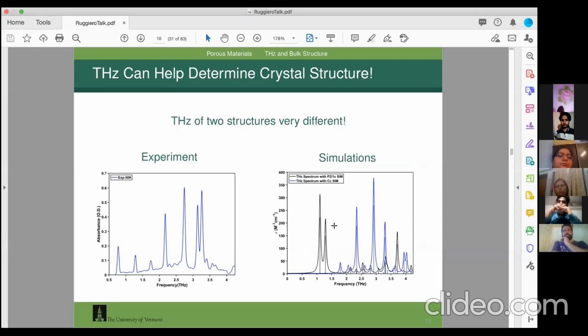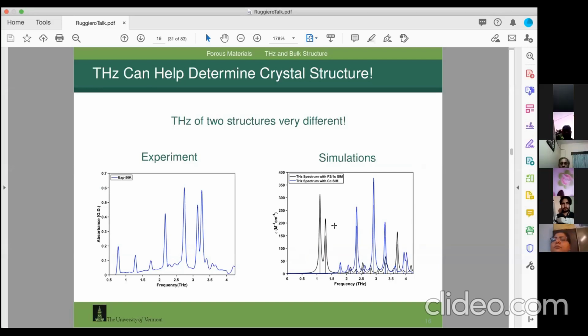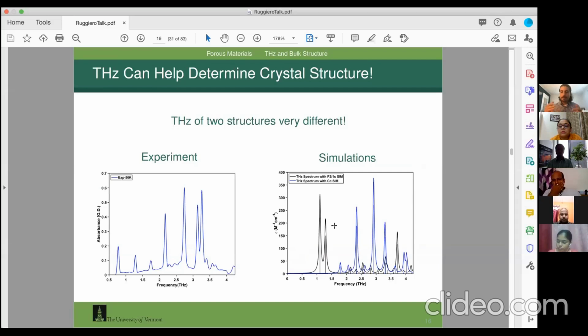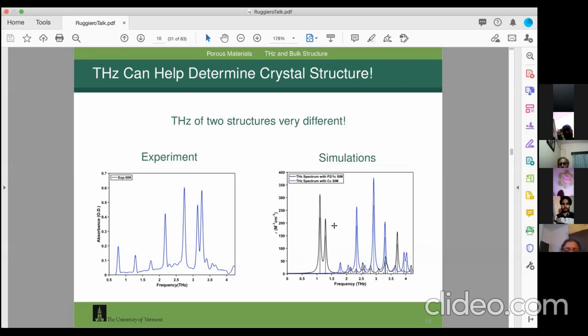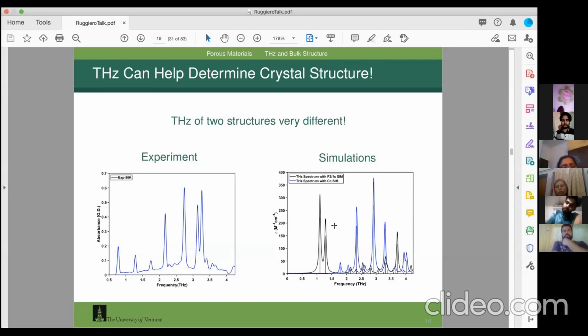And that's because the terahertz transitions are related to how many symmetry unique atoms there are. It's 3n minus 6, the number of vibrations, where n is the number of atoms. So with a smaller symmetry unique unit, you have less IR active vibrations, and so less peaks. With a bigger symmetry unique unit, you have more IR active vibrations and more peaks.